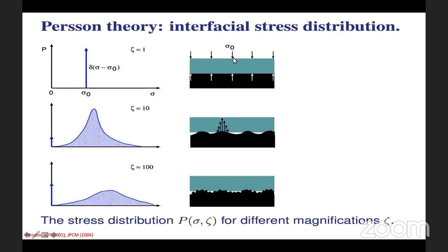This means that if you plot the stress probability distribution, you will have a Dirac delta function. This means that there is only one stress. The probability of finding that stress at the interface is very high, and it's a Dirac delta function, which is very thin and infinitely high. The area under the curve of this Dirac delta function is 1. So at the lowest magnification with the naked eye, you will have at the interface the same stress that you apply.